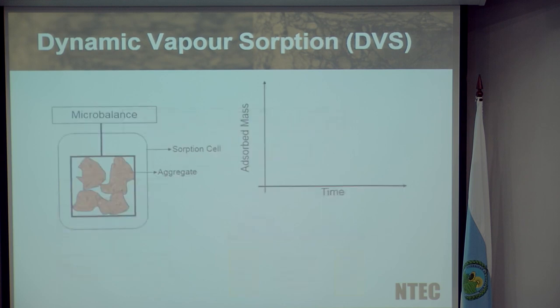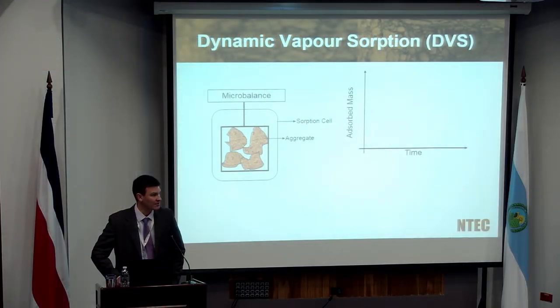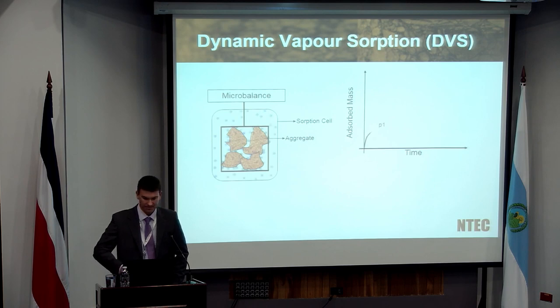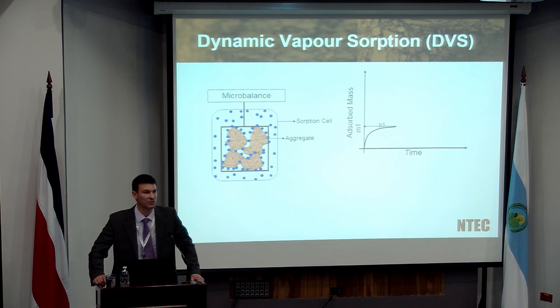I've got a very nice sketch that was developed by one of my PhD students just to illustrate how it works. If we take a sample, let's assume a sample of fine aggregate, or you could take a sample of filler, depending on the material that you're interested in, you place it into this vapor absorption equipment, which essentially consists of a very accurate microbalance, where we can very closely monitor any changes in mass, and effectively a pressure vessel, some means of forcing that gas to increase its pressure. If we then put in a gas with known properties, we would measure that absorbed mass. In other words, the change in mass as the gas molecules start to completely cover that particular aggregate sample. Whether it's fine materials or filler, it's all a function of how long it takes.